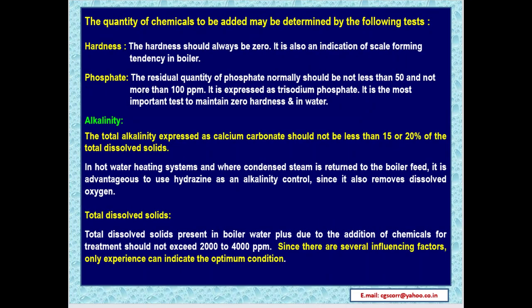The quantity of chemicals to be added may be determined by the following tests. Hardness: the hardness should always be zero. It is also an indication of scale forming tendency in the boiler. Phosphate: the residual quantity of phosphate normally should be not less than 50 and not more than 100 ppm. It is expressed as trisodium phosphate. It is the most important test to maintain zero hardness in water.